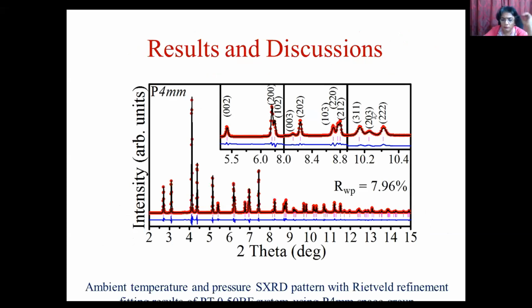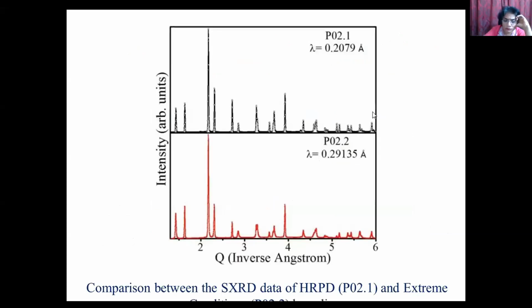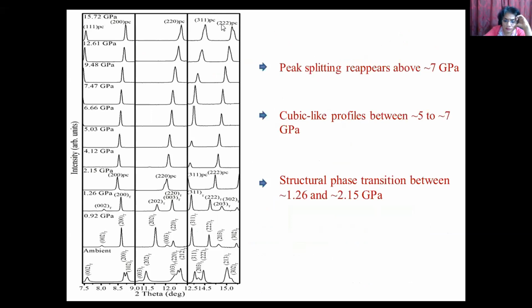This is the room temperature XRD pattern which shows a clear single P4mm space group phase, and this is the comparison by high resolution and extreme condition beamline. Here we can see the evolution of peaks. Here we can see the nice splitting of the tetragonal structure. And in this graph, this singlet peak is now a doublet peak, which gives a clear signature of the structural phase transition.